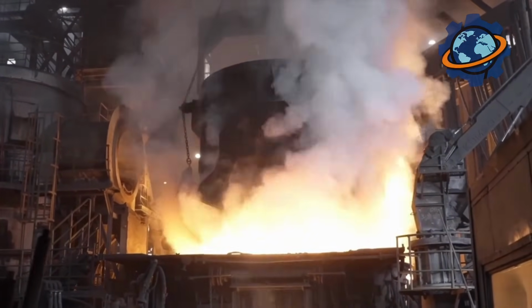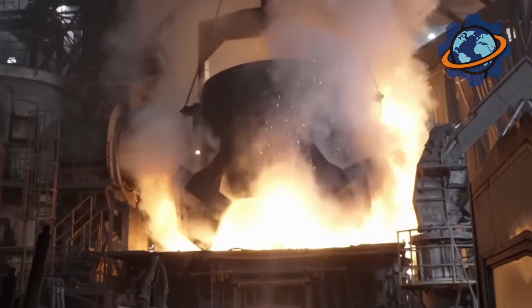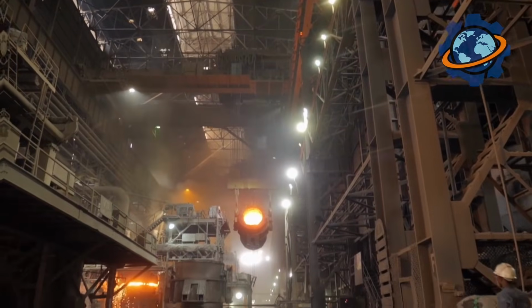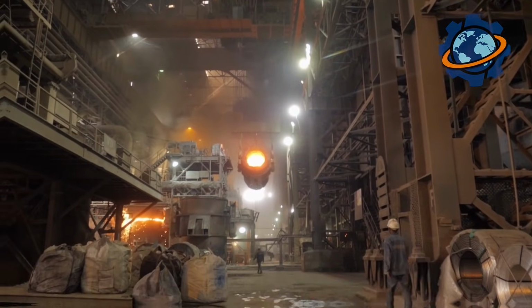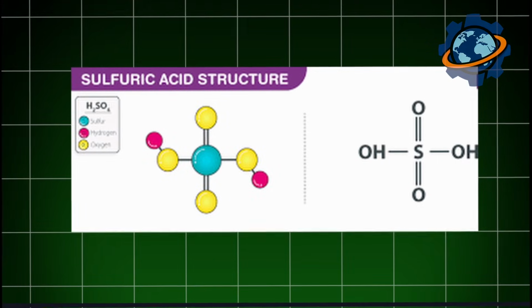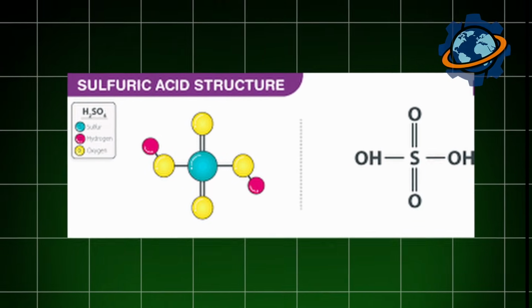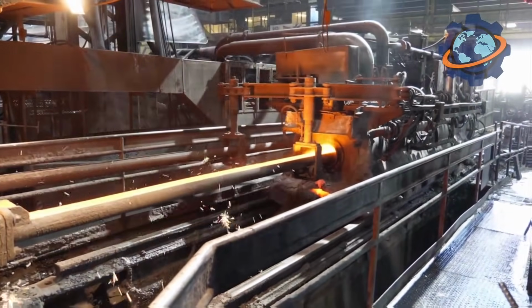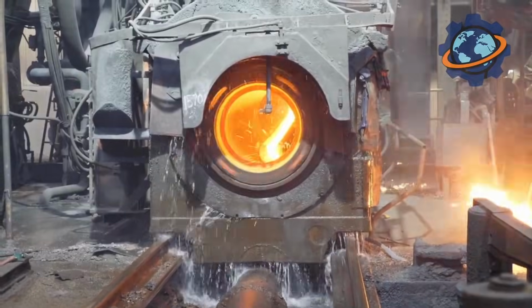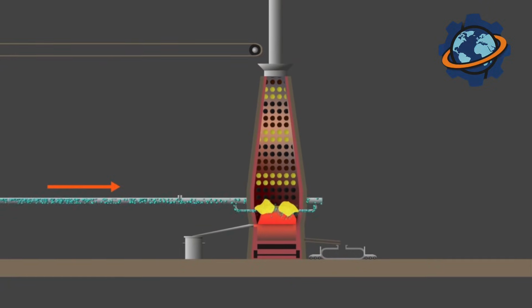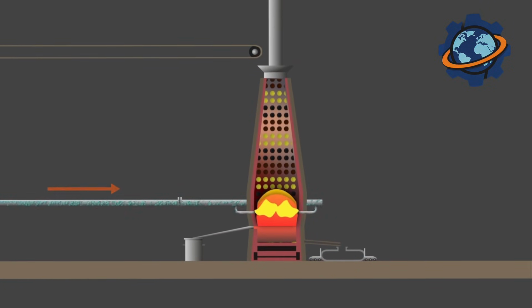Sulfur oxidizes, releasing enormous amounts of heat. Sulfur gas flies up the stacks. It will be captured and turned into sulfuric acid. And zinc sulfide transforms into zinc oxide, a gray-white powder. The temperature in the furnace is so high that the walls glow red. The roasted concentrate, zinc oxide, is cooled and mixed with coke, crushed coal. The proportion, 3 parts oxide to 1 part coke.